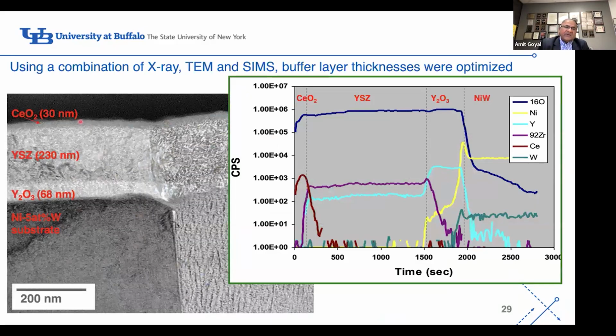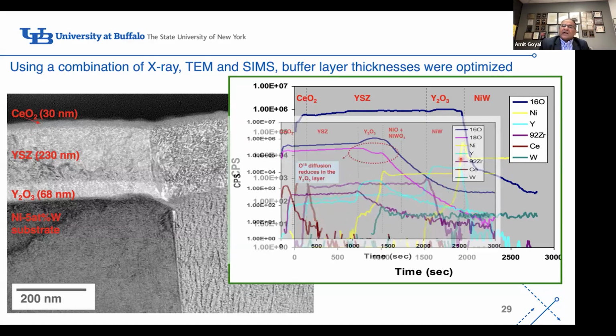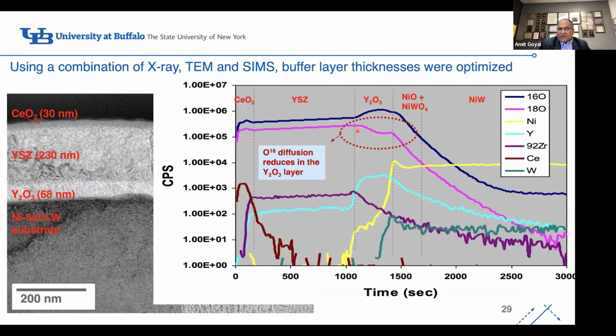When we created these buffer layer stacks, yttrium oxide, YSZ, cerium oxide, and I won't go through this, but here what we do is we try to optimize the buffer layer configurations and the thicknesses to prevent oxygen diffusion. We have yttrium oxide, which reduces oxygen diffusion, to avoid significant oxidation at the metal interface. This is SIMS depth profiling to optimize all of that.